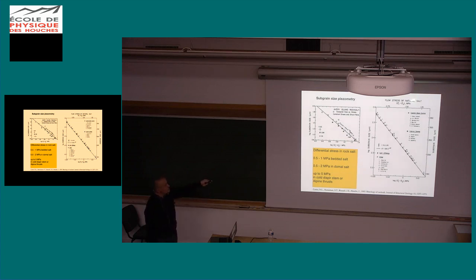And in this picture here, this is the natural salt. They derived from the subgrain size that the differential stresses are very low. Of course, we have known that, but now it's quantified. And after this, there has been a lot of additional work. So now there are hundreds of these measurements in all kinds of different settings. And we know that in very, very gently deformed bedded salt, the differential stress is rarely above 1 megapascal. In domal salt, it's mostly between half and 2 megapascals.